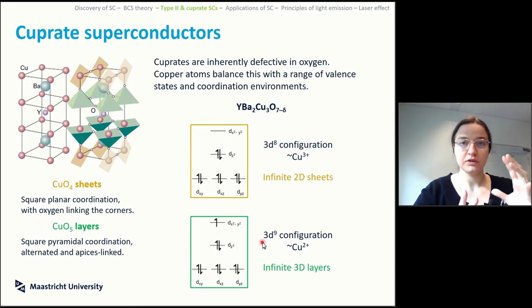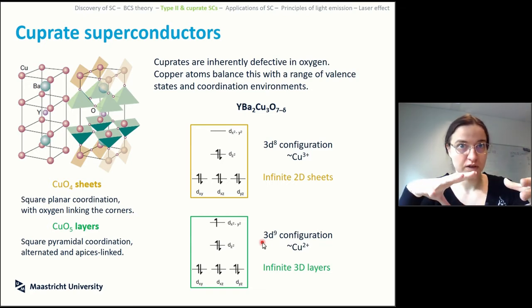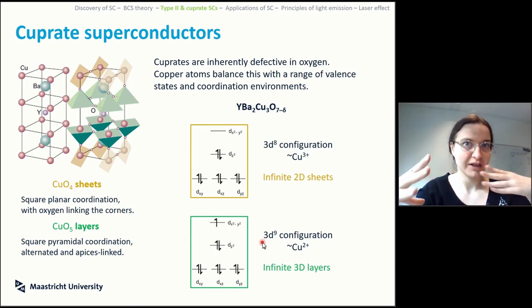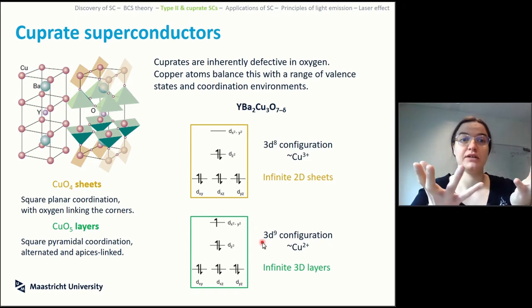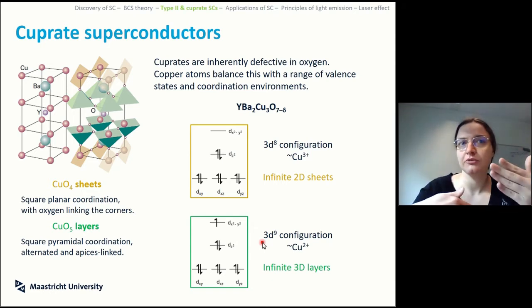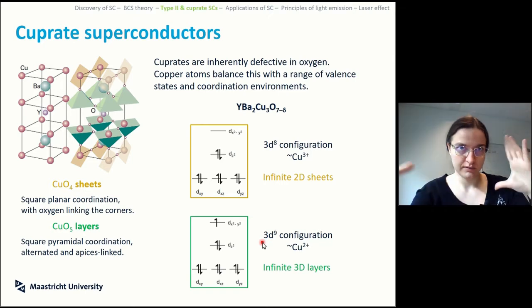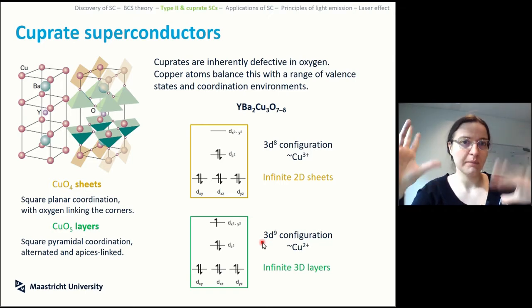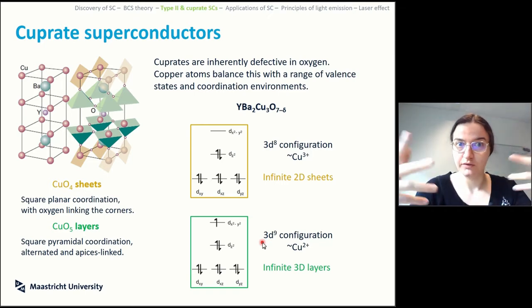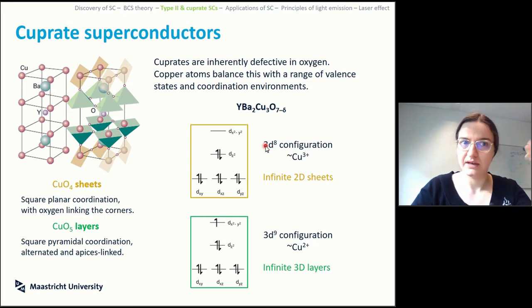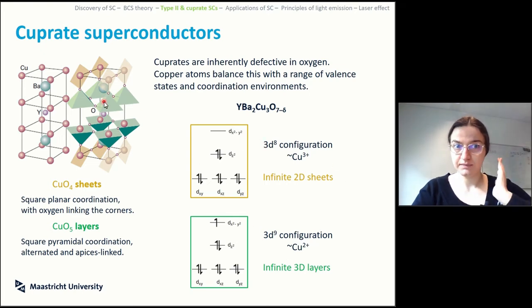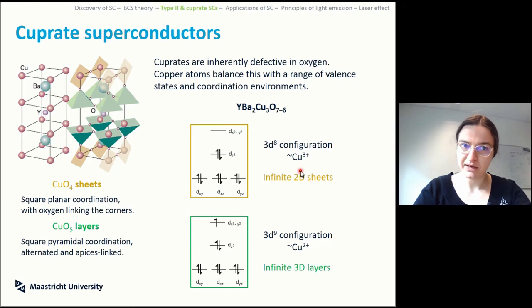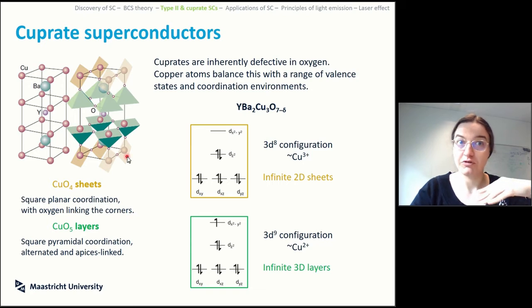So when you use the crystal field to look at what your atoms can actually do, and you put it in a solid state, you can find yourself with the same atom, different coordinations, in a crystal arrangement. That means that you have a mixture of states. So this is already interesting in itself, and this creates infinite sheets of copper 3+, and infinite layers, because you have these XY layers of copper 2+ like material.